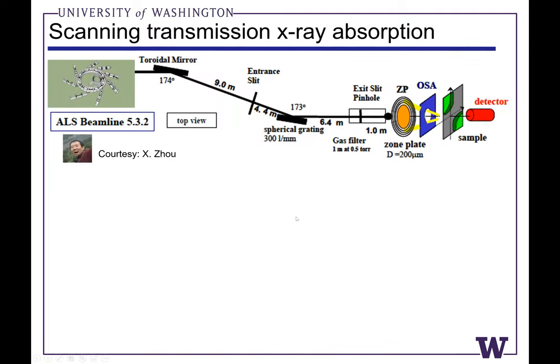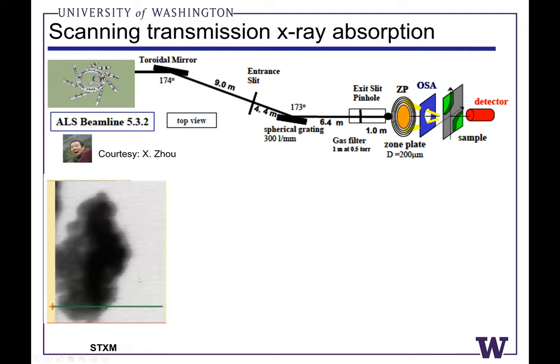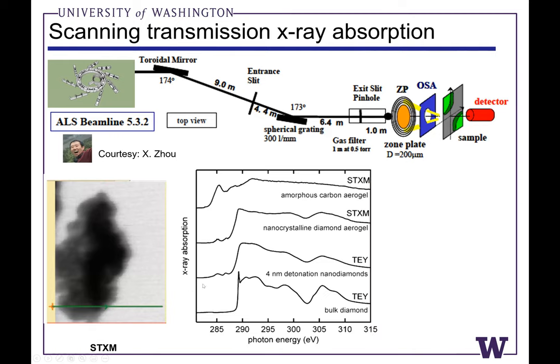but the electron diffraction. We can also recover these materials and take them to an X-ray absorption beamline. These were experiments done at the ALS beamline 5.3.2 in Berkeley. I'll spare you the overview of how a synchrotron works, but basically we have a Fresnel zone plate where we can focus a monochromated X-ray beam onto a sample with a spot size on the order of 20 nanometers. I think that the spot size is now approaching 10 nanometers at beamline 5.3.2. And we can scan over the sample and collect X-ray absorption spectra.